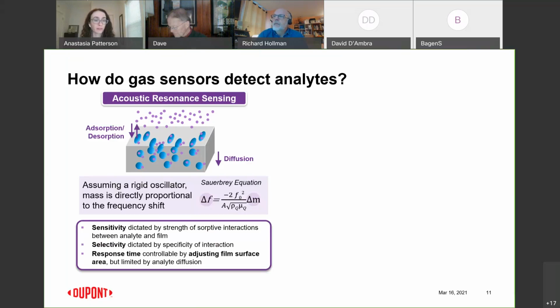In terms of material properties, the sensitivity, how low a concentration we can sense, is really dictated by the strength of those adsorptive and desorptive interactions between the analyte and the film. The selectivity, which has to do with being able to recognize a particular gas in a host of other gases in a mixed environment, is dictated by the specificity of the chemistry that we choose. So how specific can we make the chemistry on the surface to interacting with the particular analyte of interest? And the response time, to make it relevant for actual everyday use, is controllable by adjusting the film surface area. You can imagine that the more adsorptive sites you have, the more quickly you can equilibrate with the environment.